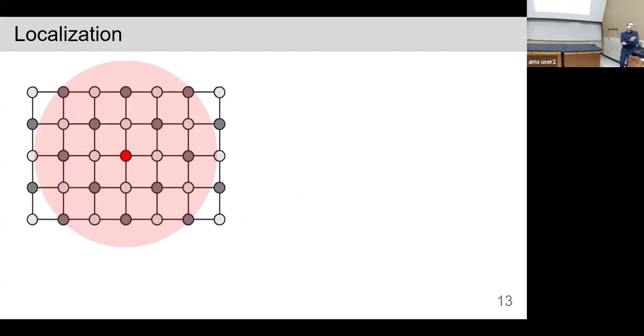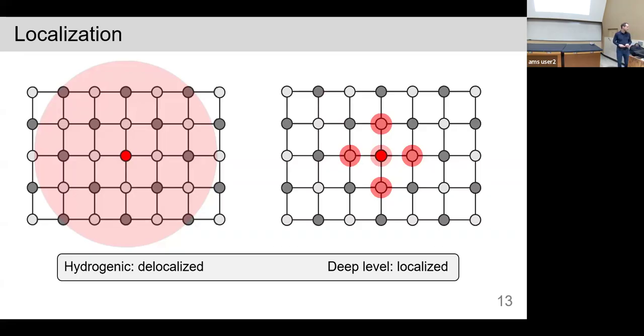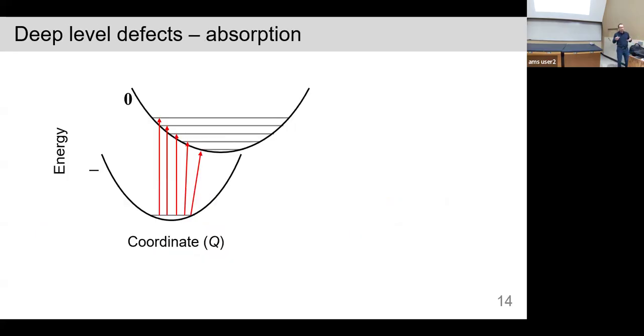So the key part of this is the question of localization of the electron's wave function, or the hole's wave function. A shallow acceptor, as I mentioned, has a large Bohr radius, and it covers many, many unit cells. And so you can treat the crystal as a continuum. So it's a delocalized wave function. But a deep level is different. This is an example of maybe I have lithium in zinc oxide, and the hole wave functions are located on neighboring oxygen atoms only. And so that's more of a chemist thing. It's more like a molecule rather than this continuum. And so the localized wave function has much smaller wave functions.